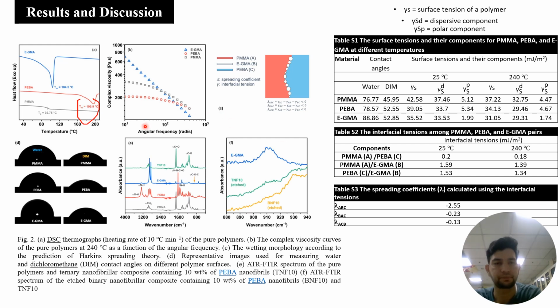In figure 2b, it is the complex viscosity of PMMA, PEBA, and EGMA, because we combine these three components in the polymer blend, at temperature 240 degrees centigrade, as a function of angular frequency. All materials exhibit typical shear thinning behavior, with EGMA showing a more pronounced effect as compared to PMMA and PEBA.